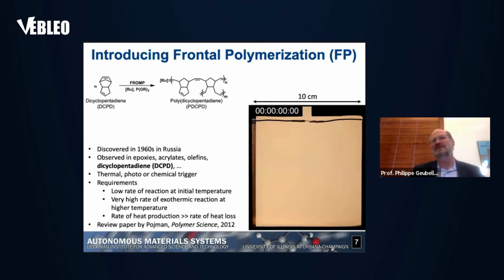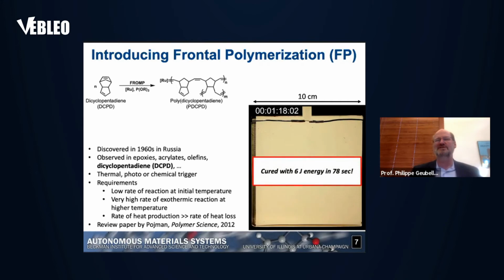So the best way to visualize what frontal polymerization is, is to look at this video. Imagine you have a little part, right? It's 10 by 10 centimeter. And what we did is we introduced a wire in there to introduce the thermal trigger. If you run the current for just a little bit, just to get it started, you can see a front that propagates. And it's a very sharp front. Ahead of the front, you have a liquid monomer, DCPD, that has a viscosity of water. Behind the front, you have a fully polymerized polymer. And the idea is that we can cure this part in 78 seconds with just 6 joules of energy. So this is an illustration of what frontal polymerization is about.